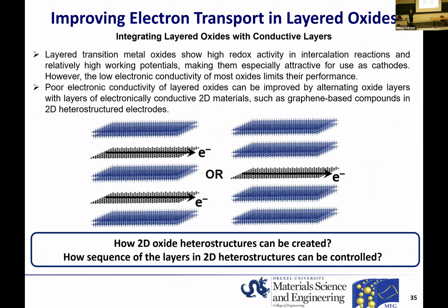In the case of layered oxides that are good for cathode applications in batteries, one of the challenges is the low electronic conductivity. There are only a few layered oxide materials that show reasonably high electronic conductivity, but most of them do not, and this could be a limiting factor in the performance.